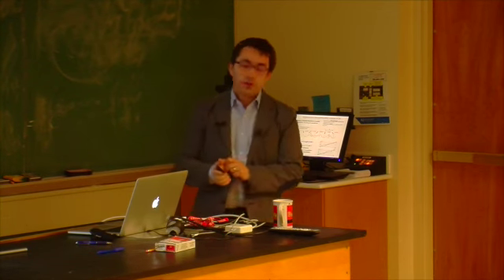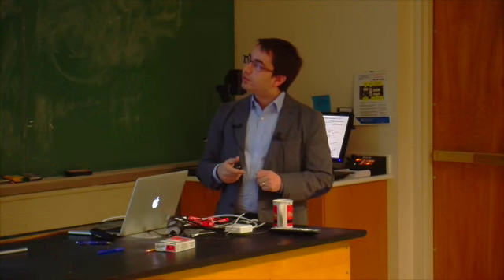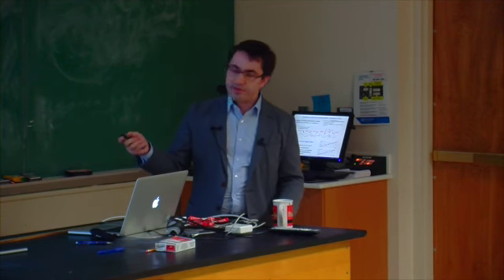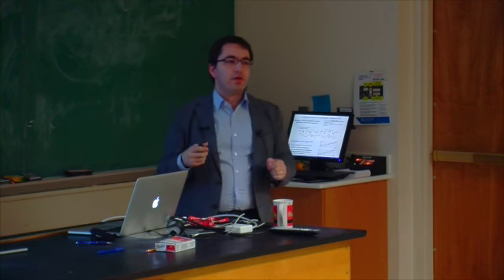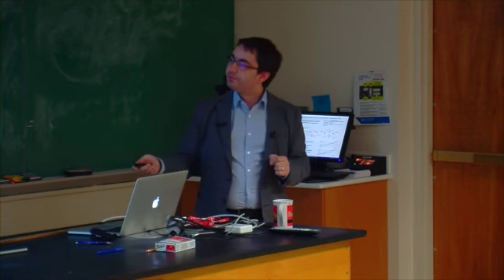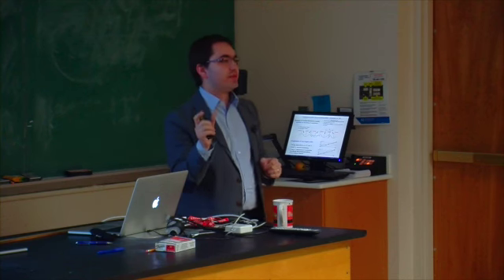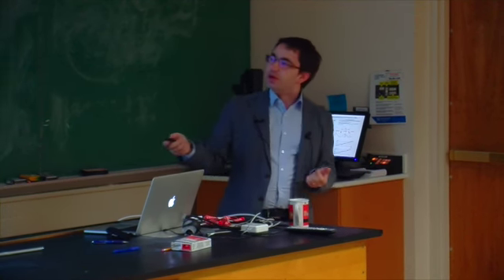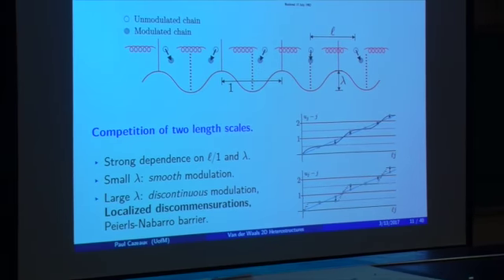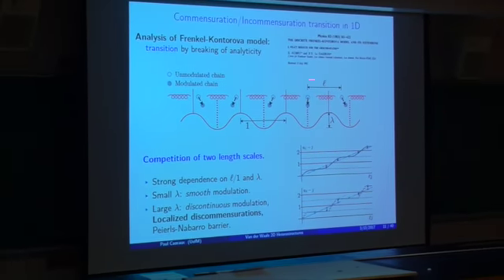A very simple, very classical model is the Frenkel-Kontorova model, which was studied in particular by Aubry and Le Daéron. This model describes what happens when we have a frustration mechanism, where we have two competing length scales. We have a chain with elastic bonds, so we can think of a chain of atoms spaced regularly with little springs in between them. This chain is then placed into a periodic potential, which has a different periodicity. At rest, if there is no external potential, this chain will at minimum energy consist of equidistant atoms separated by this lattice constant L.